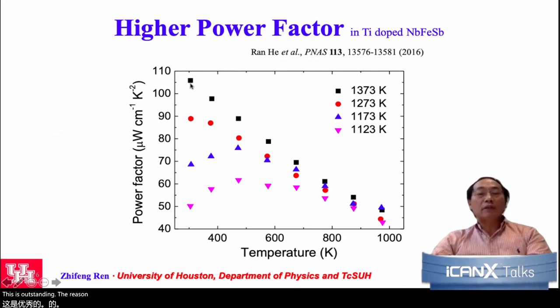The reason is because if you can reduce the thermal conductivity down to one, that kind of level, then at room temperature ZT should be close to 3. But unfortunately, so far, we have not been able to reduce the thermal conductivity. The thermal conductivity at room temperature is still somewhere between 10 and 20.